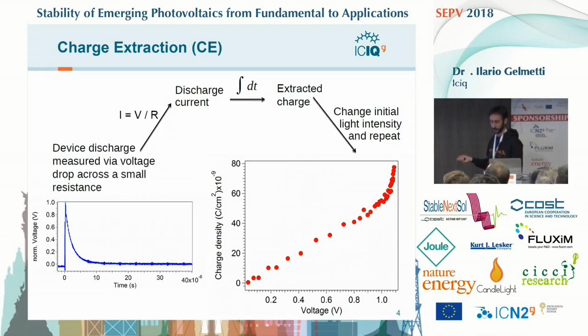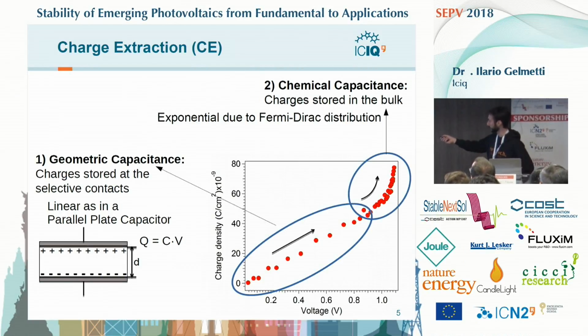We repeat changing the initial background light intensity, so that we observe the charge stored in the cell at different open circuit voltages. And that's the result of the technique. As you can see, there is a linear part that we can interpret based on the geometric capacitance, which is basically like if the cell was working as a parallel plate capacitor. So the charge stored is just proportional to the open circuit voltage and represents when the charges are stored in the electrodes. When the electrode starts to get saturated, the charges start to get stored in the bulk of the material, so in the perovskite, and we can see an exponential part, which basically the shape just depends on the Fermi-Dirac distribution in the material.